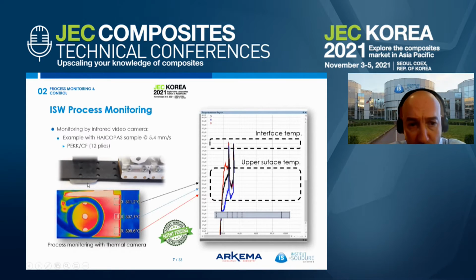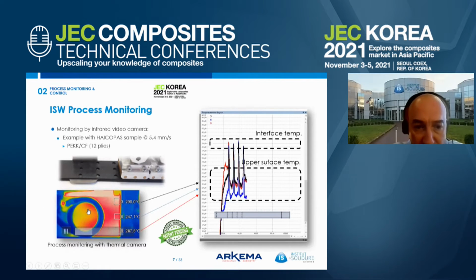Yeah, you have the mobile susceptor that is located between the two substrates, the metallic susceptor, and we will be facing from the top using a thermal camera, I would say the setup. And we can see on the video, you can see the coil and you can see all the holes that will allow us to access the temperature at the interface. So with our technology and with the setup that we actually patented, this is a perforated sample, we can access both surface temperature and interface temperature.